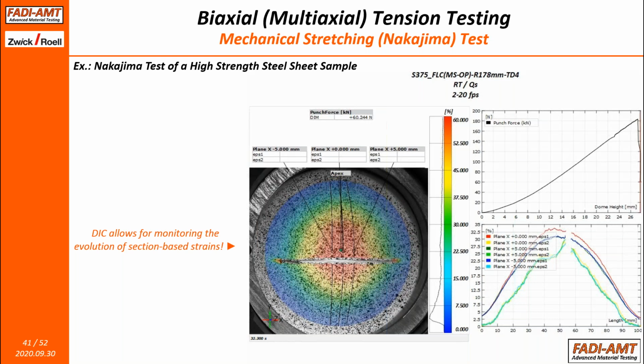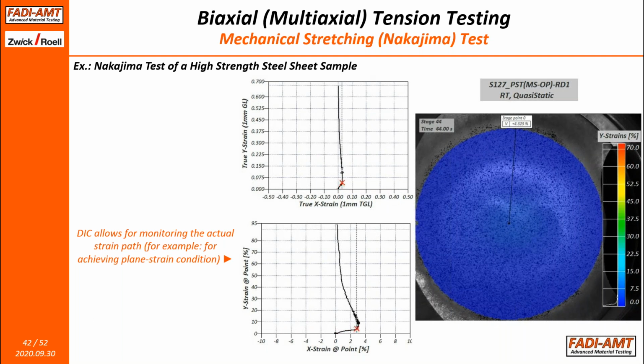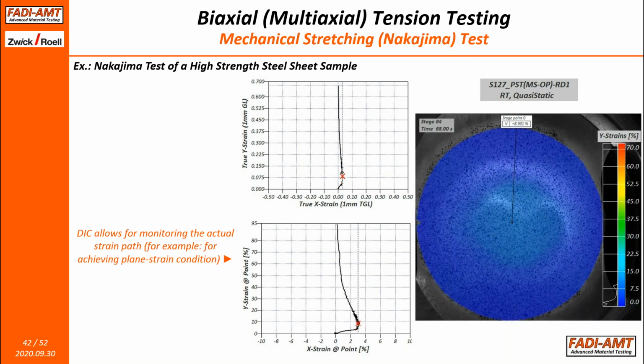There's a second method in the ISO now, which is the time-dependent approach. And the time-dependent approach, or approaches actually, there are multiple of them, rely completely on the use of any strain measurements that tag basically the amount of strain to time. And without DIC, you really cannot track and measure those effective strain accumulations up to the point of failure. And so that's where it's uniquely used to support this kind of testing. One last example, a couple of examples about the use of DIC with this kind of testing.